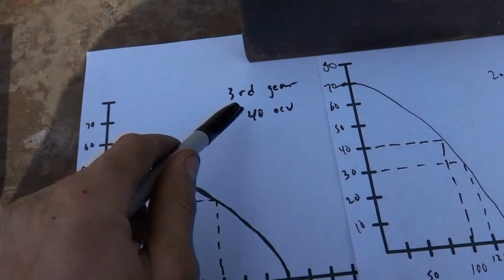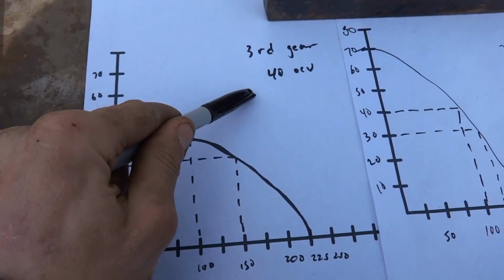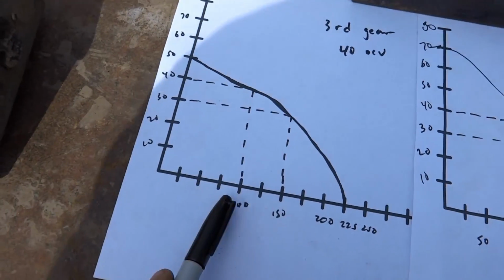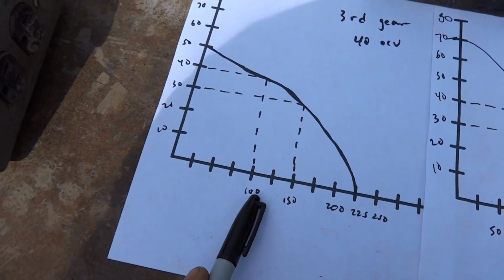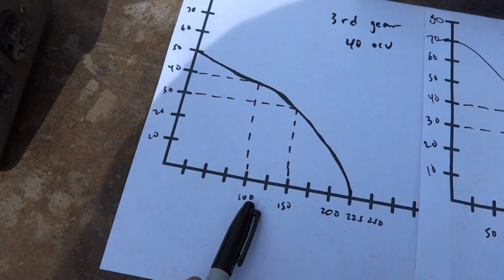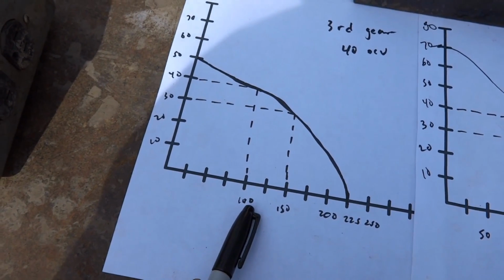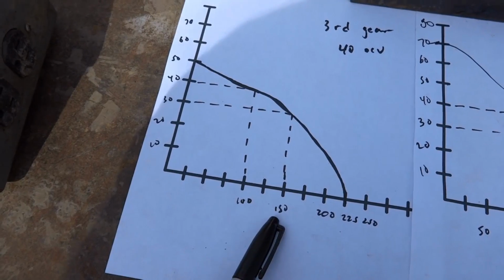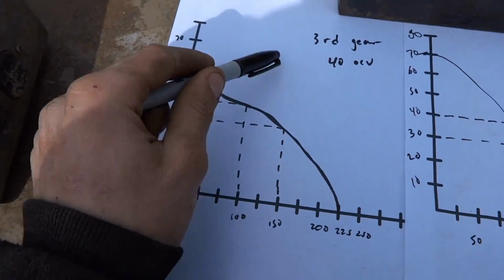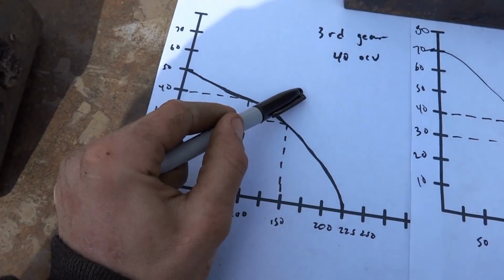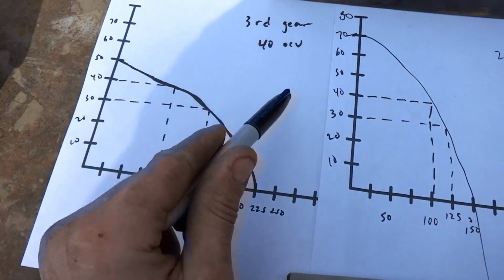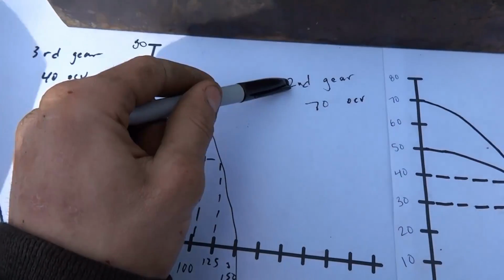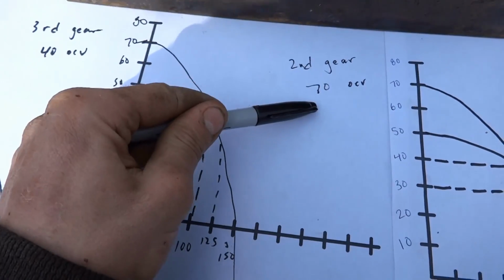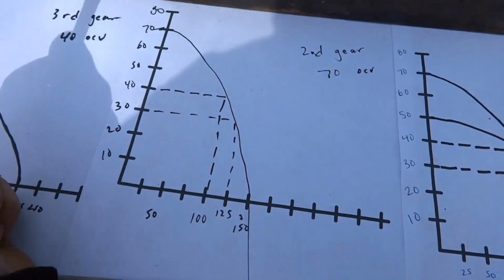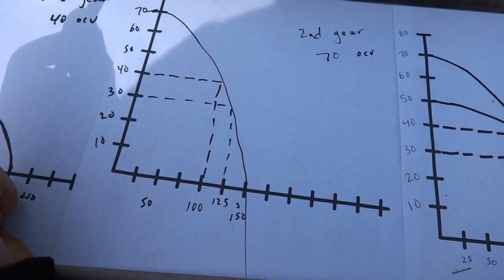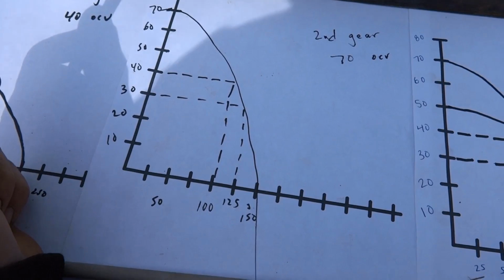Compared to running a high amperage and low voltage setting, where using arc length manipulation, a tight arc increases amperage and decreases voltage, a normal arc decreases amperage and increases voltage. There's a more dramatic effect on the amperage and voltage using a high amperage and low voltage setting, such as third gear 40, than there is running a low amperage range and high voltage setting, such as, say, second gear 70, or second gear 80 or 90 or 100.